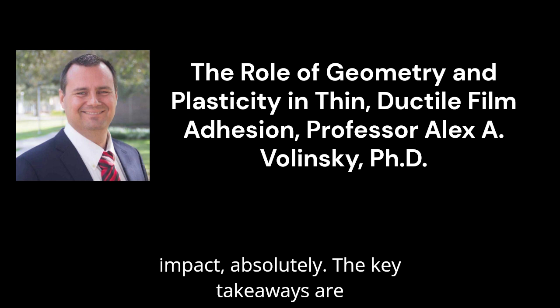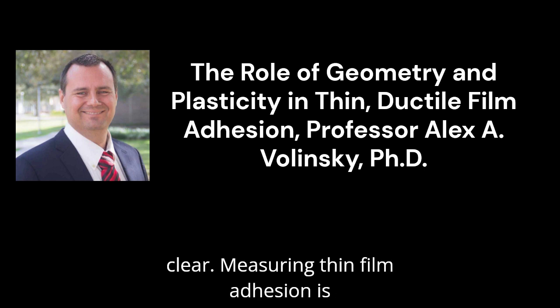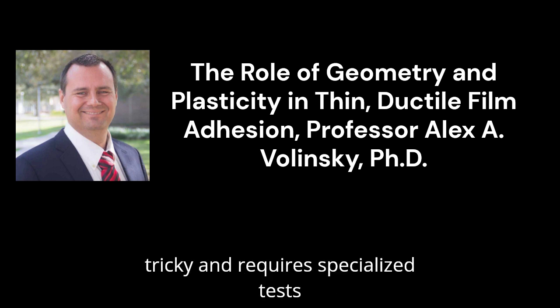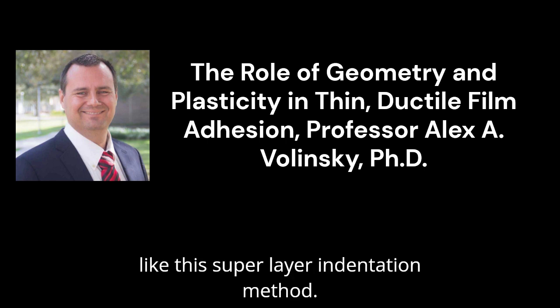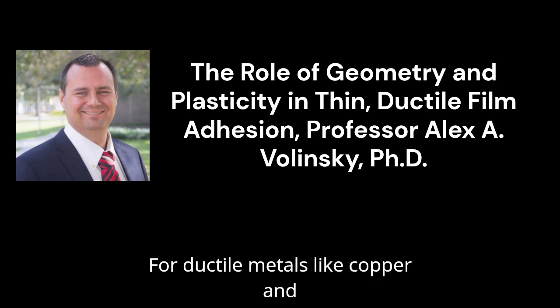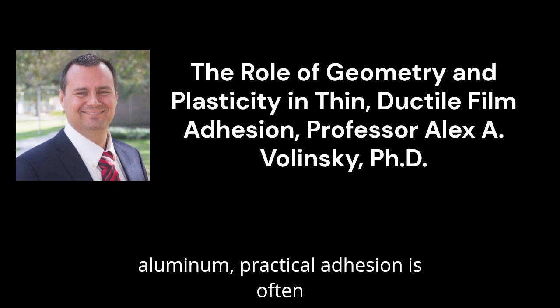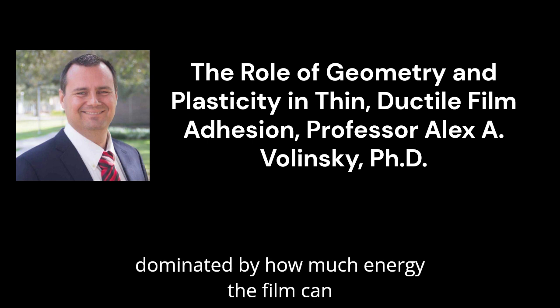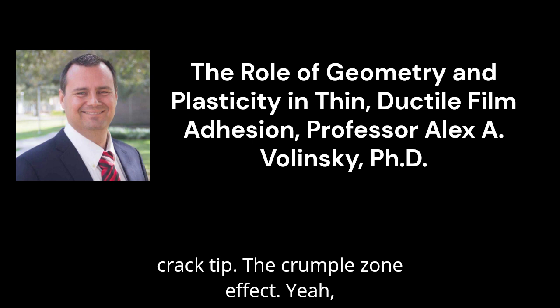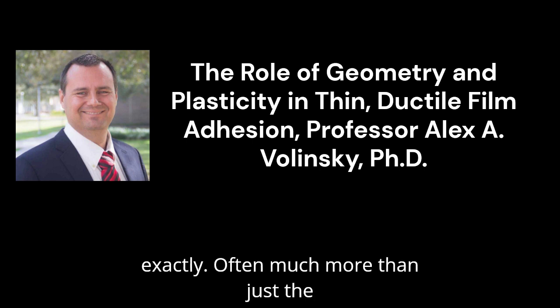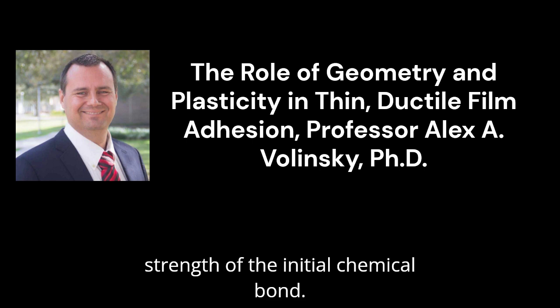That's the real-world impact, absolutely. The key takeaways are clear. Measuring thin film adhesion is tricky and requires specialized tests like this superlayer indentation method. Right. For ductile metals like copper and aluminum, practical adhesion is often dominated by how much energy the film can absorb through plastic deformation at the crack tip. The crumple zone effect. Yeah, exactly. Often much more than just the strength of the initial chemical bond.